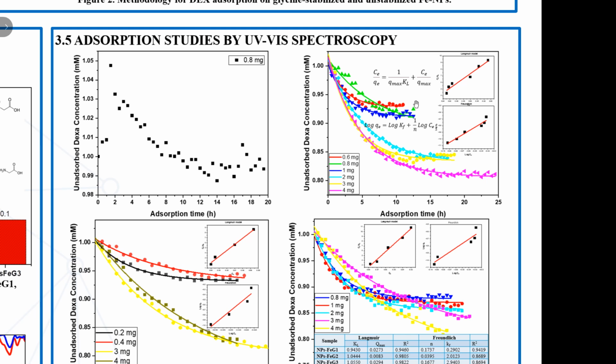And here, one more, it shows the Freundlich model, and it is used when the absorption sites cannot be assumed as uniform and there is an energy distribution. It is applied when heterogeneous absorbents are considered, and it's expressed in this form.